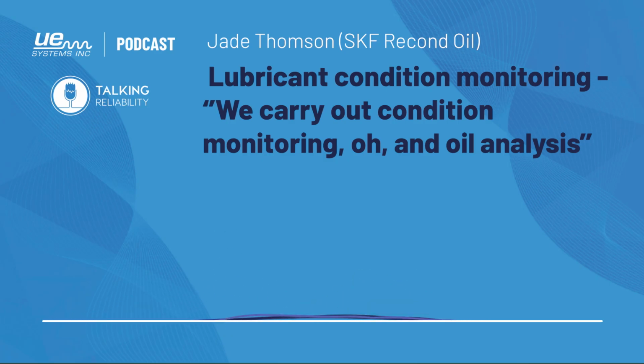If they'd have also been doing vibration at the same time or ultrasonics, they'd have definitely been able to root cause. But if we just look at the table on the right, it shows us the different categories of analysis. So on the right, we can see that iron is the main contributor there. So we should be looking at our assets and seeing what have we got in there, which is iron, chromium, copper. We can see it's quite a serious bearing and gear failure. Hopefully the people in the room that are used to analysis can see that.